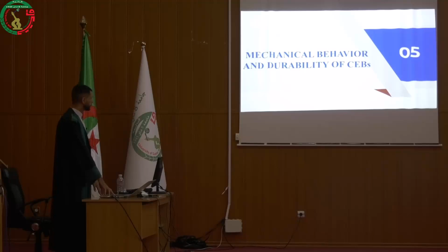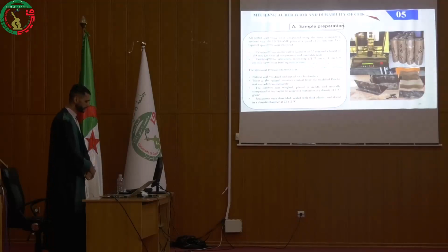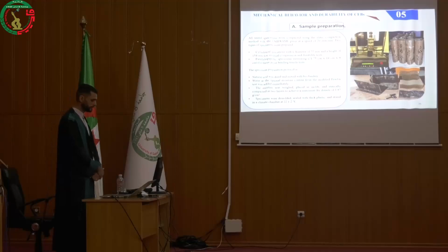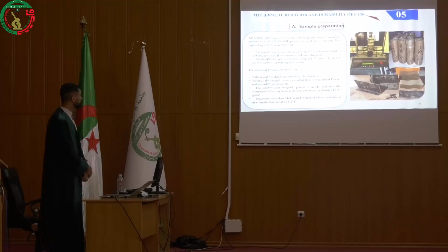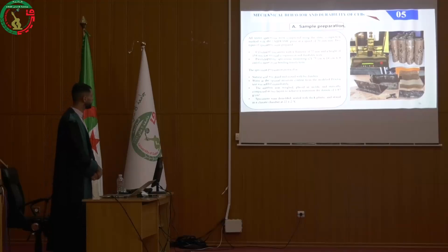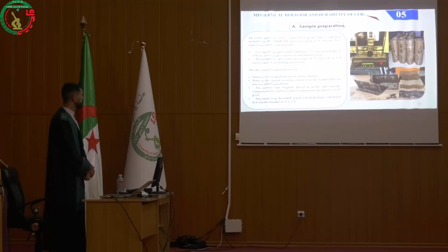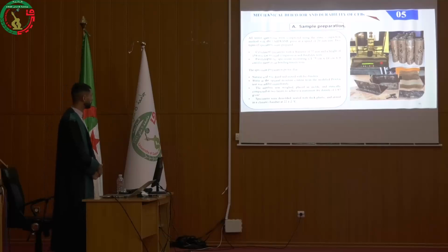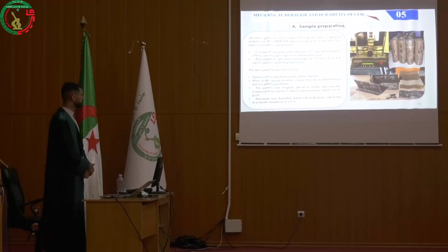Mechanical behavior and durability of the CEB. Before diving into the mechanical behavior and durability of our construction materials, let's begin with sample preparation. All tested specimens were compacted using the static compaction method with a uniform press at a speed of 20 mm per minute. Two types of specimen were prepared: cylindrical specimens with a diameter of 77 mm and height of 154 mm for unconfined compression and durability tests, and parallelepipedic specimens measuring 21.75 by 14 by 9 cm for the 3-point bending tension test.